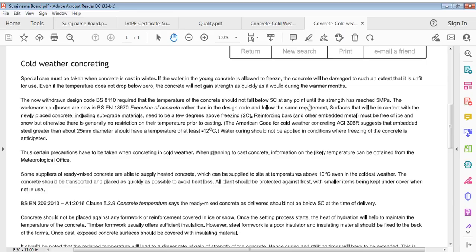Surfaces to be in contact with newly placed concrete, including subgrade materials, need be a few degrees above freezing, 2C. Reinforcing bars or other embedded metal must be free of ice and snow, but otherwise there remains generally no restriction on temperature prior to casting. ACI 306, which is referred to, suggests that embedded steel greater than about 25 mm diameter or 1 inch should have a temperature of at least 12, not -12, so 12, okay. Water curing should not be applied in conditions where freezing of concrete is anticipated. So we should not use water there because it says 12 degrees Celsius.